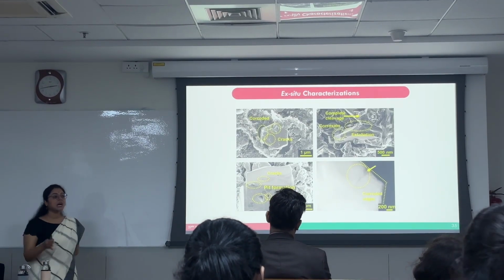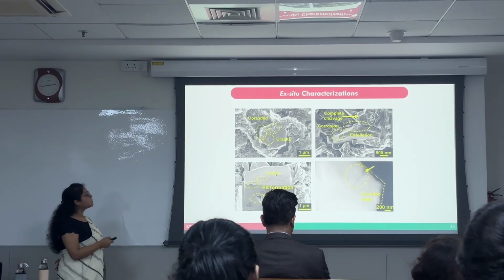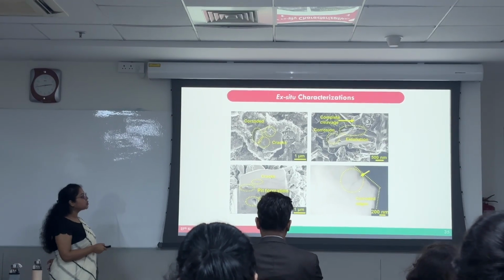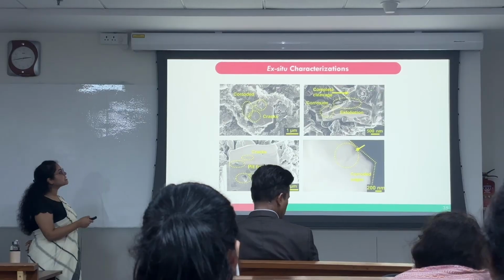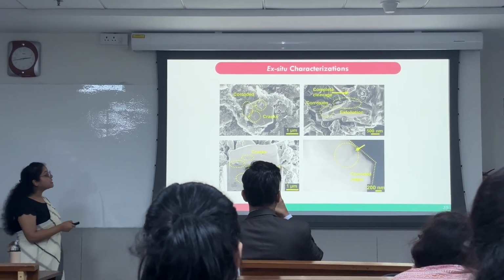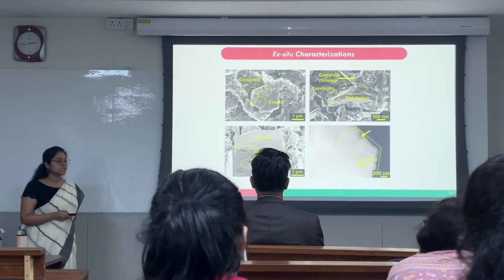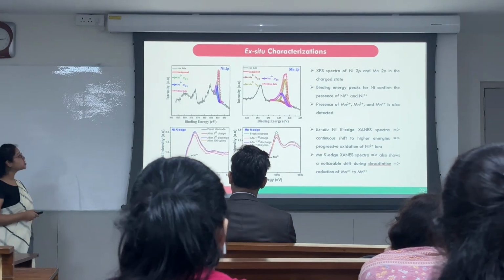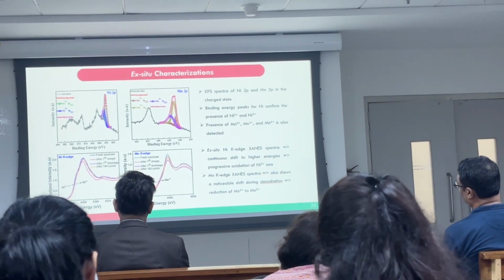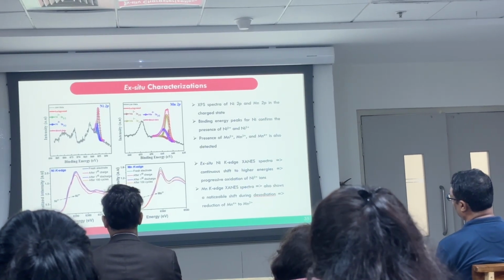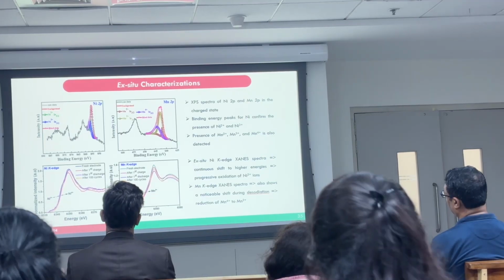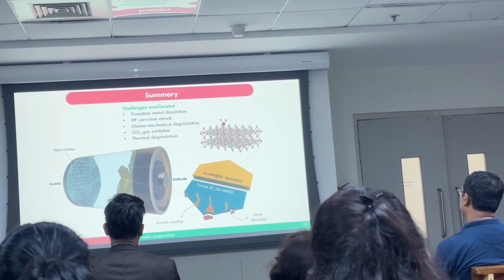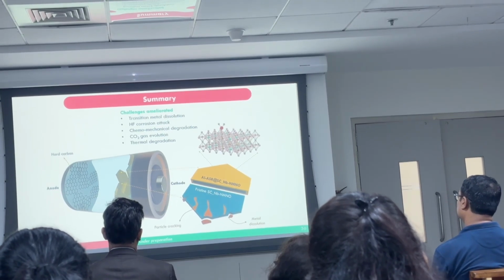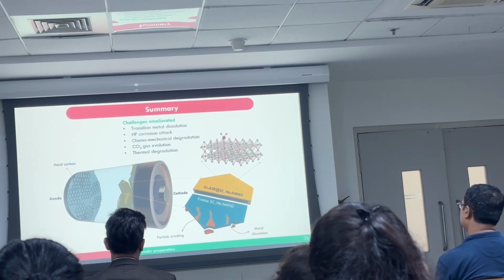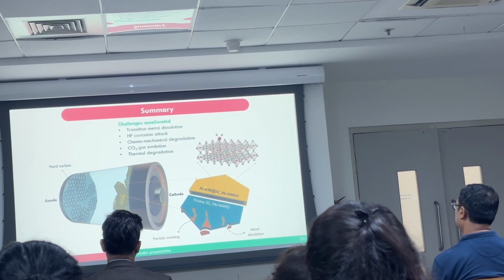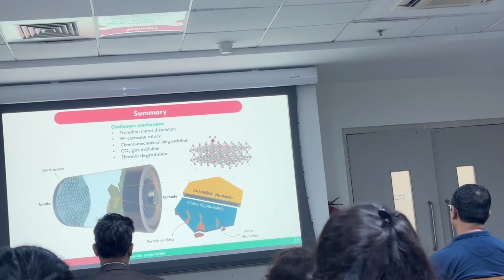Further, to see how the chemomechanical degradation is happening, we did the SEM as well as some FIB-SEM analysis and high angle annular dark field imaging, which easily shows the cracks, the complete cleavage, corrosion, exfoliation, pit formation, and the corroded edges are also very well visible in the primary crystals. We then analyzed the charge compensation mechanism using the XPS, and we saw that at charge state, the nickel as well as the manganese are both active, and also through the XANES analysis, we observed the activity of nickel as well as manganese. Thus, in this particular chapter, we dealt with the challenge of transition metal dissolution, HF corrosion attack, chemomechanical degradation, CO2 gas evolution, and thermal degradation by adopting the strategy of coating the cathode material with trimethyl aluminium as a precursor.